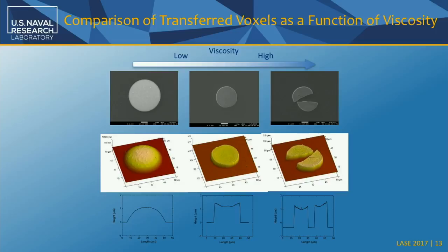On the other hand, here, when we have the right viscosity, we end with what looks like almost a thin film. And there are no masks, no patterning, no material removed, and we can get very precise patterns. Of course, if we remove too much solvent from that suspension, then our transfer falls apart and breaks while it's released.